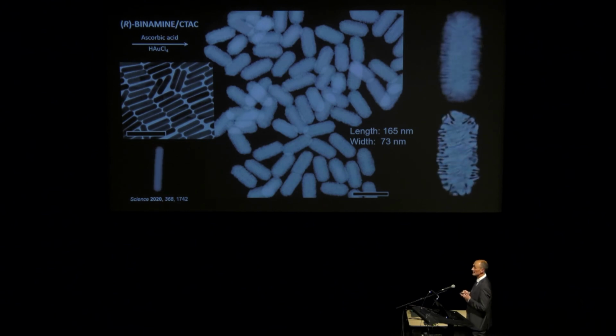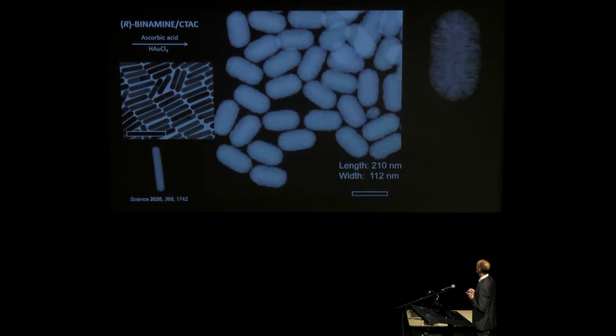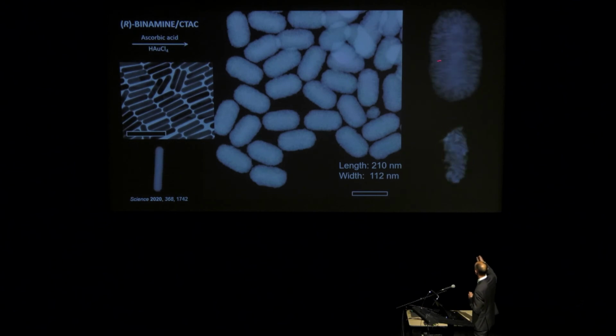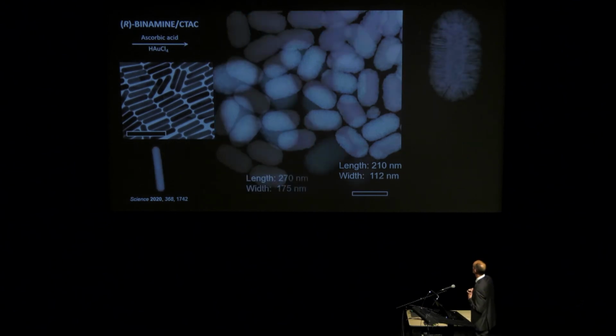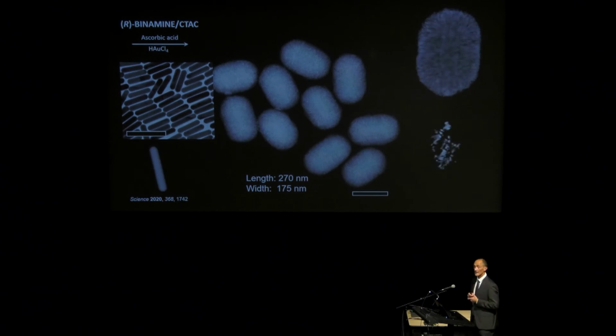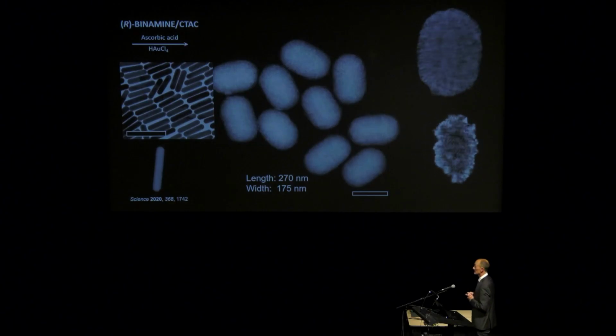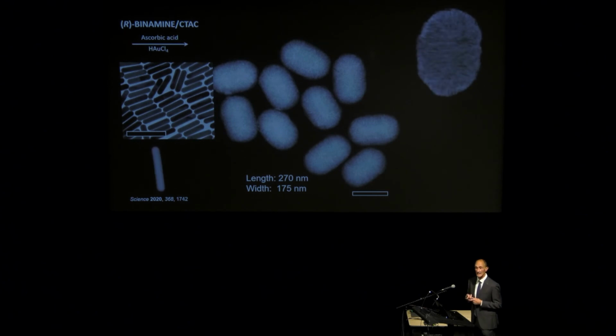If we now increase the amount of gold that is reduced on the same number of nanorods, we obtain similar grown rods where the center is still exactly the initial solid nanorod, and now the grooves grow even longer and even longer. And this is quite interesting because this really confirms that the micelles are templating the growth of gold on the surface. Now, how can we confirm that there is chirality here?